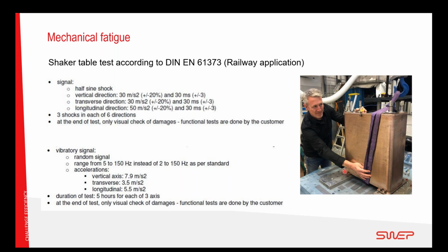And it's a typical installation. You can see here, it's a heat exchanger we have tested. We have increased the number of plates to get the most extreme dimensions. We have the interface downwards. You have connection plates. So we have the 4-inch ports facing down, and often it's mounted onto the engine block directly like this. And it's also one of the preferred installations that we have. And we are brazing the connection plates to the heat exchanger simultaneously as the whole unit is brazed. And then we have a flat milling on the connection plates, so we make sure we have very tight tolerances to the interface to the engine block.